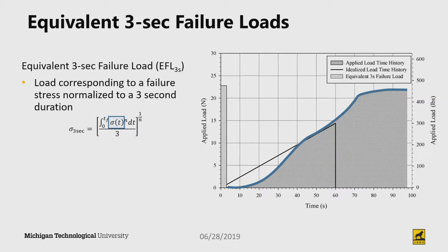But whatever it is, ideally we'd have some ramping load, but that's not always the case. It's certainly not the case when you use full scale. And we want to bring this back to some common time, so we're just going to use this integration technique to recenter it, normalize our duration, in this case to 3 seconds.